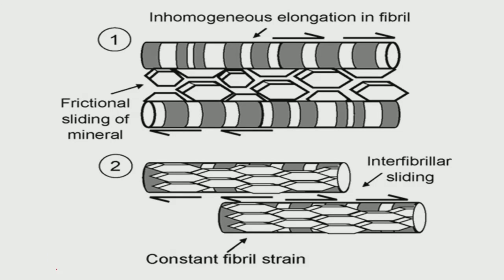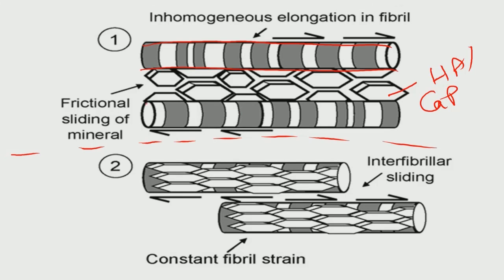So there are two types of scenarios shown here. Scenario number one is when hydroxyapatite or calcium phosphate phases are present between two collagen bundles. So this is one collagen bundle and this is a second collagen bundle. What is shown here is that the collagen bundles will experience some kind of shear stress, and the presence of this shear will make the collagen bundles slide over each other, slide over the hydroxyapatite platelets. These hydroxyapatite platelets will experience more of a tensile stress, as I explained in the last slide.